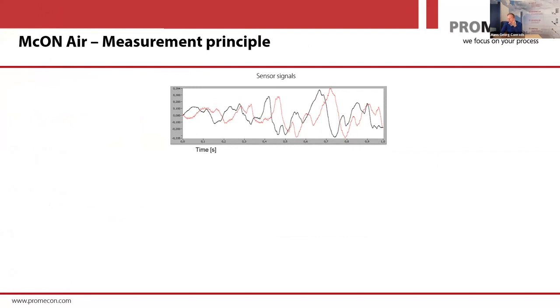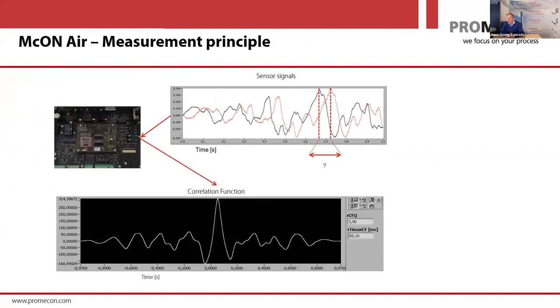What you do is you digitize these two signals, and you don't care about their magnitude. You don't care about their amplitude. The only thing that you care about is their statistical match. So you digitize them, you put them into a cross-correlation filter, and out you get the cross-correlation function. The cross-correlation function is basically showing you a maximum at the time shift where the two curves have the best statistical match. So you basically shift them on top of each other and you move them. And wherever they match best, you have this maximum in your cross-correlation function.